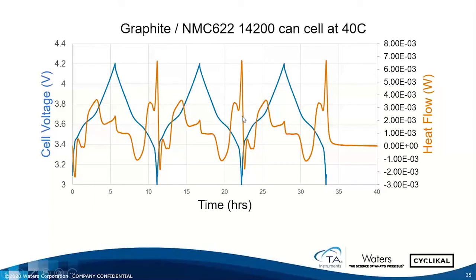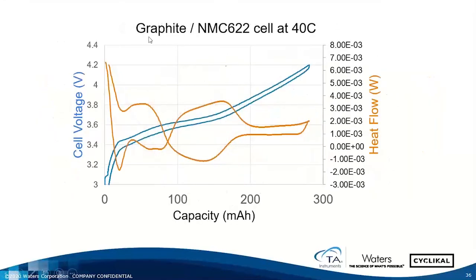All of the features that you see in the thermal signal are entropic effects. So for example, when we charge the cell and we get to the switch point, which is right here from the thermal data, you see a sudden change in the thermal power. That's an entropy change. Okay, so if we wrap that around the switch point here and plot it against capacity, you get this plot here, which is reminiscent of the symmetric cells, and you can see the symmetry of the reversible heating.